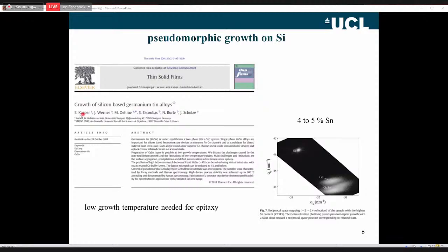Kasper, I think his first name is Eric. Eric Kasper has many papers in this field: silicon, germanium, tin. They found, in one of the early growth papers, that germanium-tin can be grown epitaxially on a germanium layer on a silicon substrate. So we have a silicon substrate, a germanium buffer layer, which is relaxed, and then a germanium-tin layer, and they can be grown in a coherent epitaxial way.